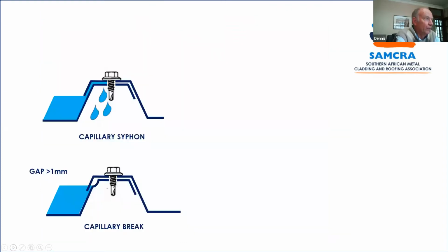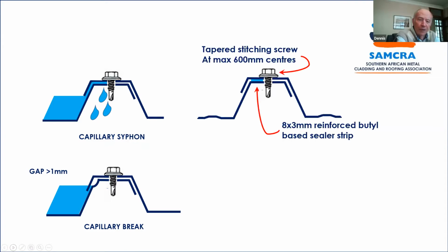And if you would like to, there we go. And of course, with conventional pierce fix, that's your corrugated iron and your IBR profiles, once the depth of water in the pan gets to the lip of the side lap, a capillary siphon is developed and moisture gets taken into the interior of the building. And effectively, if you look at that bottom picture, to create a capillary break, you need a 1 millimeter gap, and literally a dent in the top knuckle of that one rib will solve your problem.